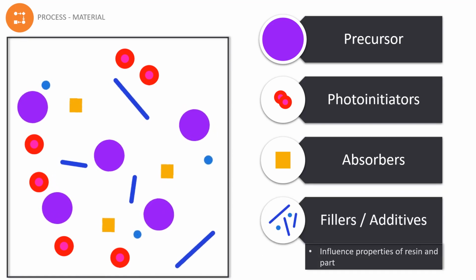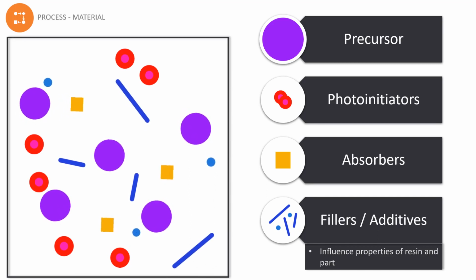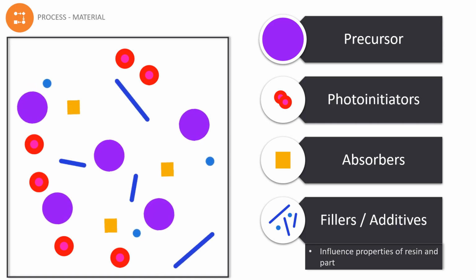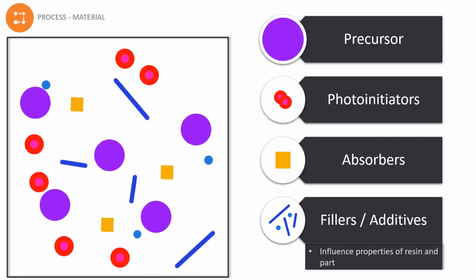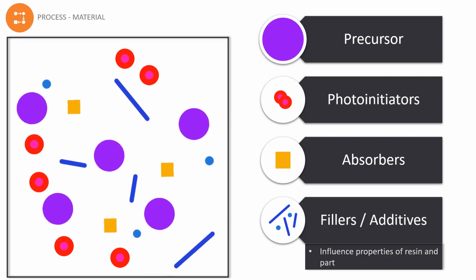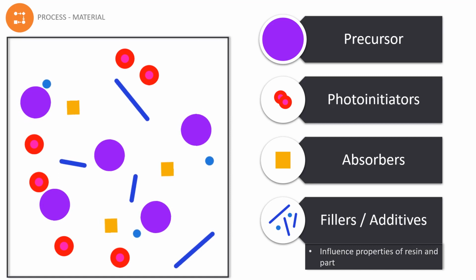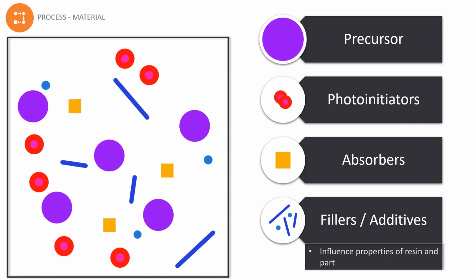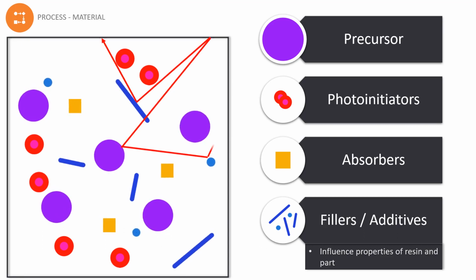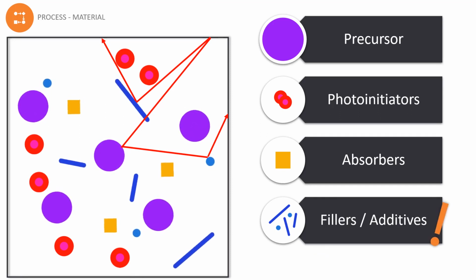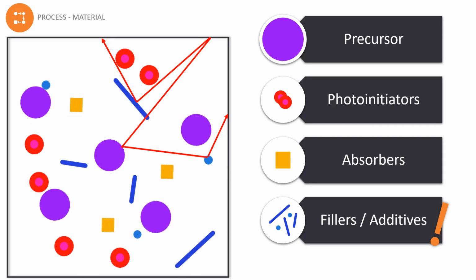Last but not least, fillers and additives can be added to the resin. They are used to influence mechanical, thermal, optical, or even electrical properties of the part. Additives are also used to obtain better flow parameters of the liquid resin because they can reduce the viscosity. The problem with fillers is that they can show a different refraction angle than the rest of the matrix. When the laser hits an area with a high filler content, it might be deflected. This can lead to printing impurities and failures. When adding fillers and additives, the refractive index difference therefore has to be considered and minimized.